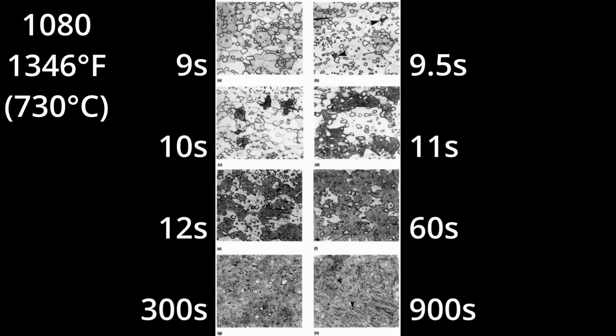But at lower temperatures, there are these cool micrographs from an old study where they used 730 Celsius, 1346 Fahrenheit. And at that temperature, the soak time, so it's already heated to 1350 Fahrenheit, and they hold it for different periods of time. It took 5 minutes to fully transform the steel from ferrite to austenite. At that point, there are still carbides left, but it's finally austenite, so that when they quench it, it's the dark martensite that they look at under the microscope.